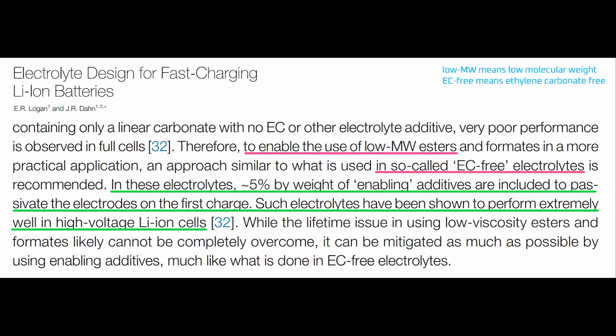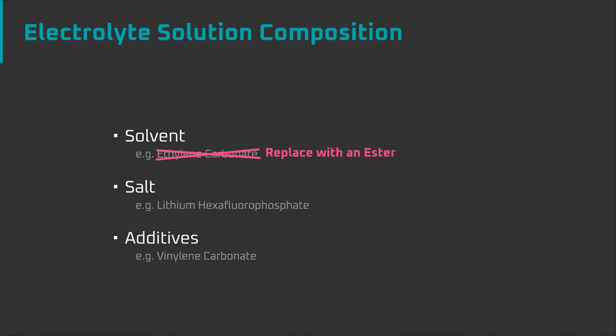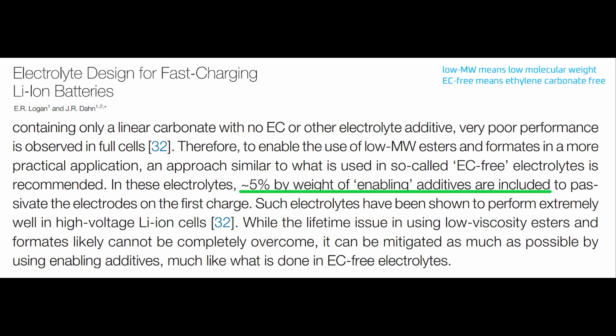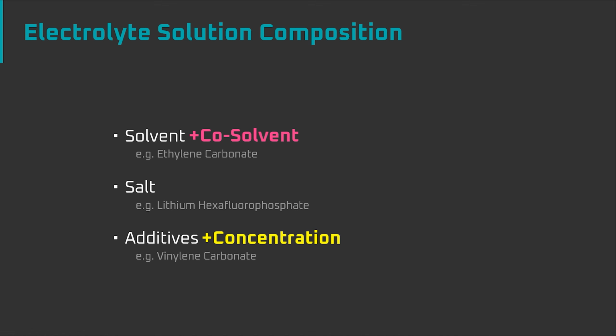Jeff's team suggests that an electrolyte using 5% additives mostly solves the cycle life issues. For reference, my understanding is that a typical additive loading is more like 1 to 2%. The additives are usually kept to a minimum because they can be expensive. What all this means is that there are solutions available to mitigate the cycle life issues inherent with low viscosity solvents like esters. I doubt CATL used one of the exact formulas in the research papers I've just shown here, but they likely used a similar approach and borrowed from them.